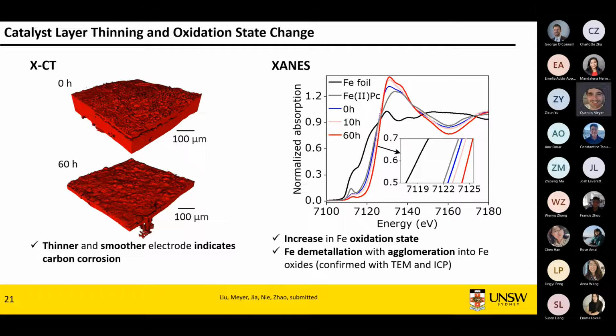So what we did instead was we made one sample, scanned it, then we made a new MEA and we scanned it again. But they look overall very similar in terms of main features of cracks, but there's a very clear difference. This is about 100 microns thick. This is about 10 to 20 microns thick. So you lose about 80% of thickness. Also, what's interesting is the electrode surface is much smoother, and that's typically a signature of carbon corrosion. When your electrode collapses on itself, agglomerates, and basically just becomes a much smoother, much thinner material, because you corrode your carbon.